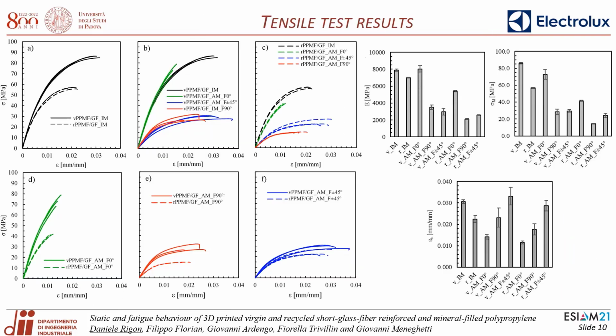Let's now have a look at the tensile test results. The first graph, letter A, shows the engineering stress-strain curves of the virgin and recycled specimens produced by injection molding. As you can see, the recycled matrix degrades the Young's modulus, the tensile strength, and the elongation at break of these specimens. Figure B reports the comparison between the virgin material produced by injection molding and pellet additive manufacturing. It is interesting to note that the F0 degree specimen has the same elastic properties of the IM material, since the curves are well overlapped at the beginning.